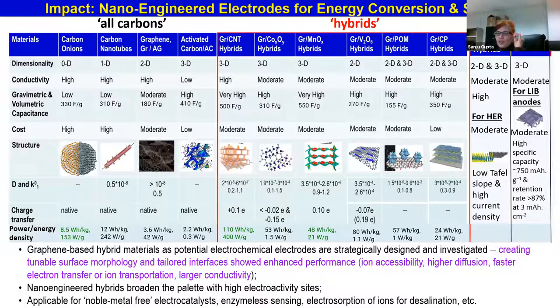Off the top of my head, it depends on their operating conditions and what electrolytes they use. There are a lot of parameters which play a vital role. People usually don't report these, but it should be reported that way: even the area, the size of their electrodes. There are a lot of parameters missing in the literature, and people report just values, saying they got a high power density or high specific energy density, but nobody really knows what's going on behind the scenes. The carbon onion values are taken from the literature, and the others come from our study. Okay, so these subtle differences can play into these numbers.